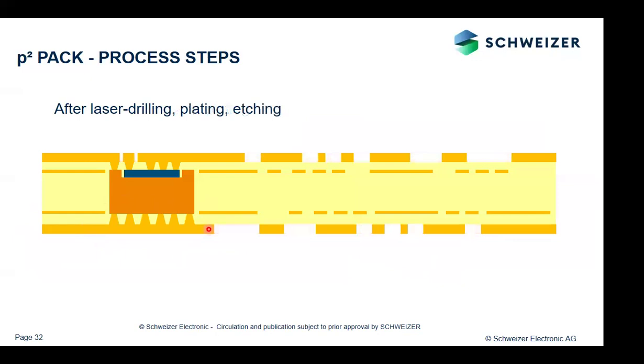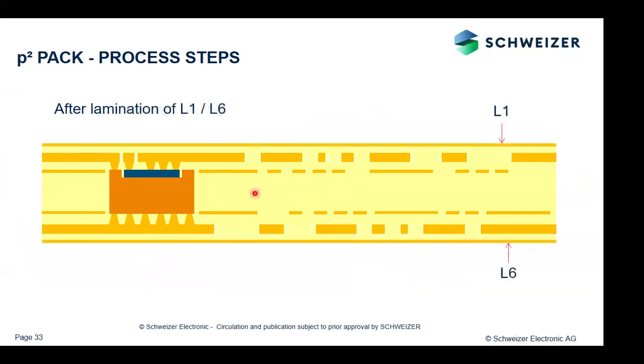So after that, you also go through a print and etch process to create the outer pattern. And in this stage, you have a 4-layer multi-layer, and the power stage is more or less ready. You could stop here and you would have an electrical functional power stage. But what we want to achieve is an intelligent power stage. And therefore, we are adding 2 more layers at the top and at the bottom. It's 2 layers due to symmetry, because if you would only add 1 layer at the top or 1 layer at the bottom, it would start to warp.